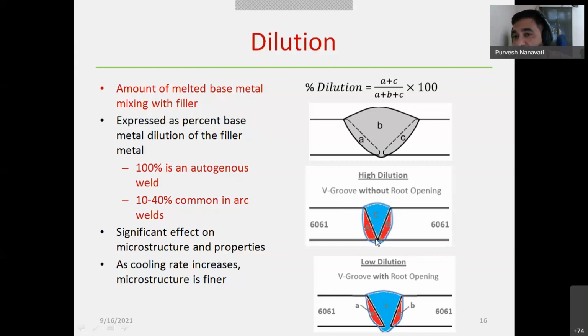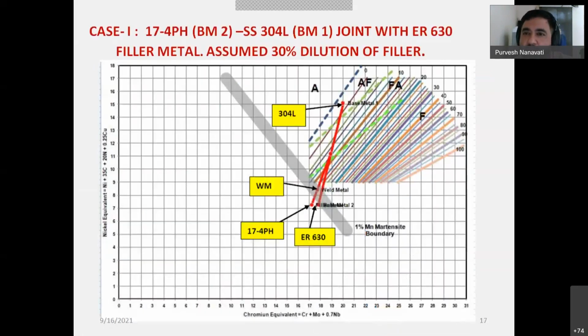So design is also an important aspect, but this dilution has to do with the weldability, because the contribution of the base metal into the weld metal will change the whole scenario, its microstructure and its mechanical properties. Most of the time, we use a compatible filler metal for the joining of two similar metals and two dissimilar metals. So this is a case study to understand two different metals: 17-4 PH, that is 17 chrome and 4 nickel precipitation hardened steel grade, and stainless steel type 304L. This is a case study.